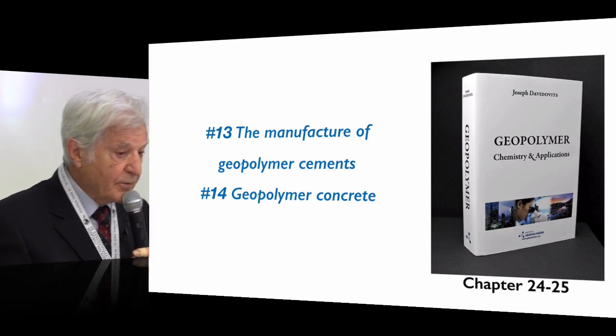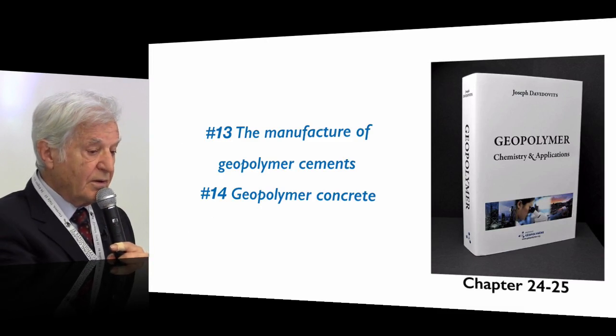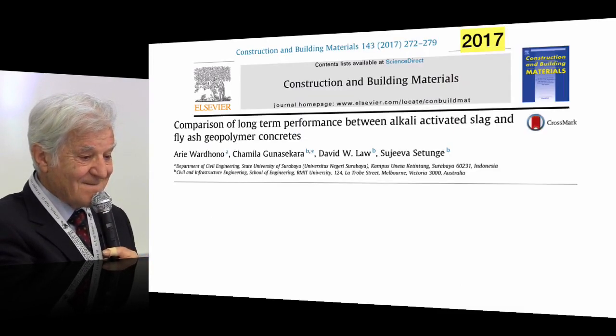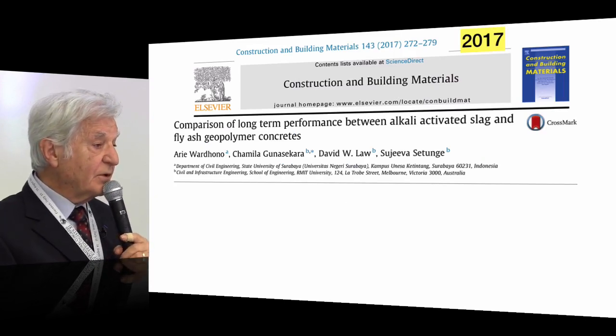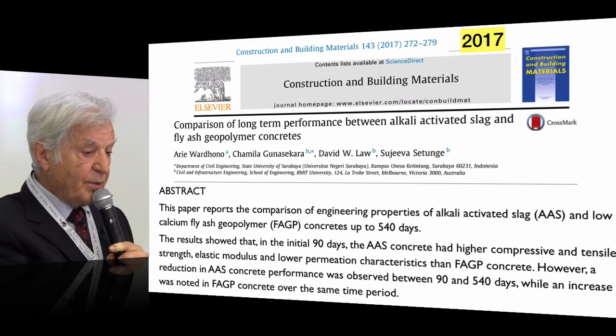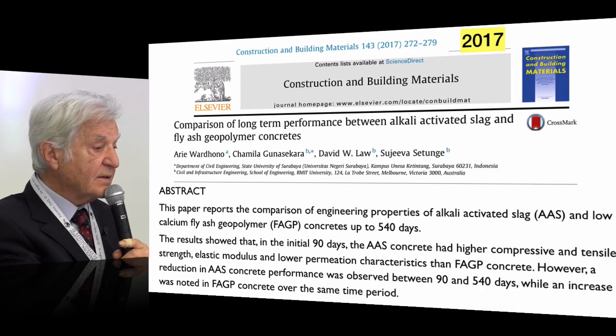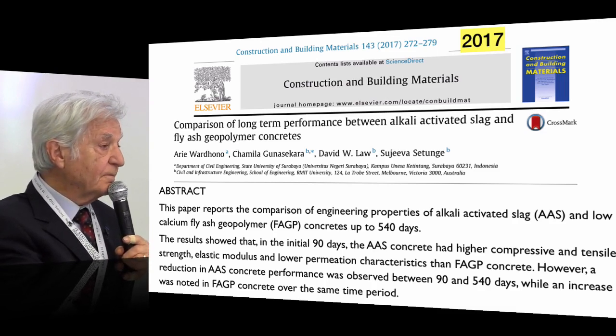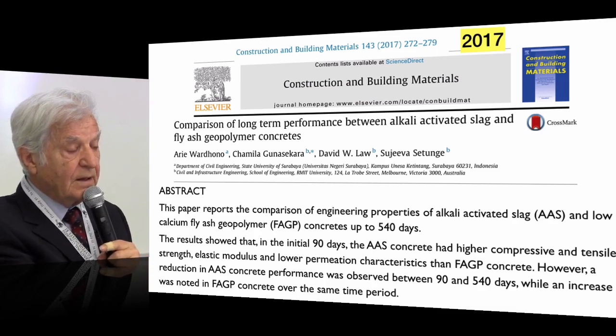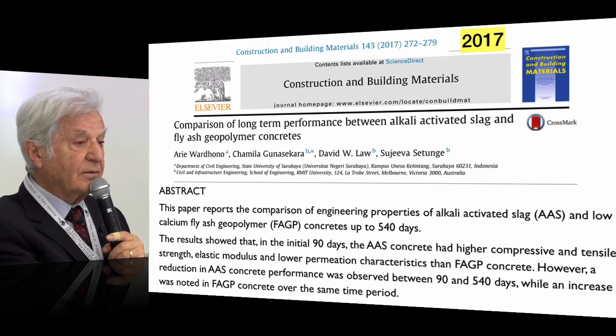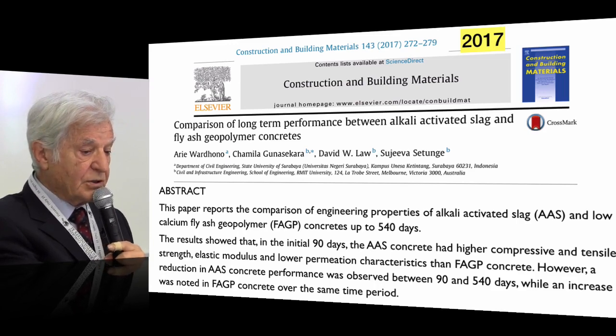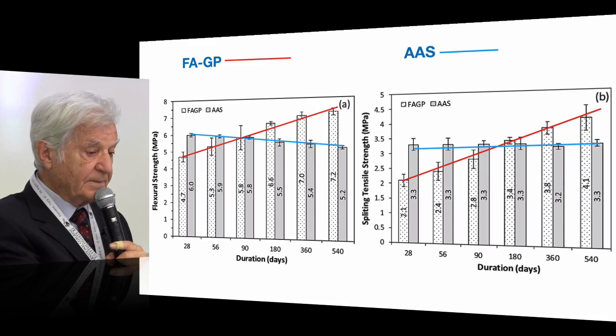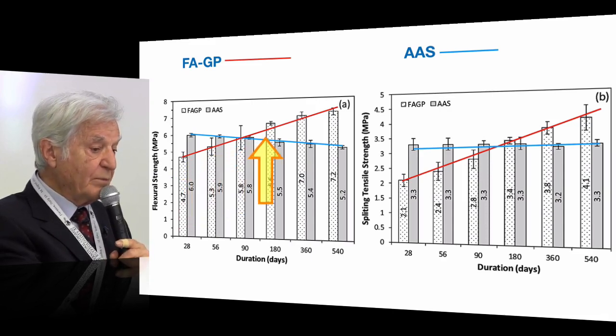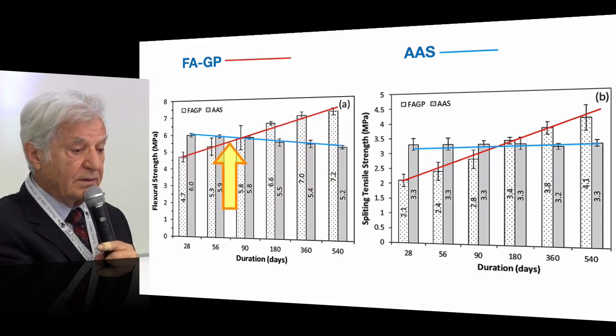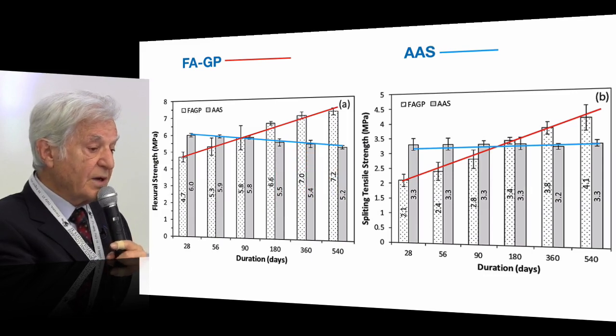Topic number three, the manufacture of geopolymer cement and the manufacture of geopolymer concrete. I present here a paper that I found very interesting. 2017, comparison of long-term performance between alkali-activated slag and fly ash geopolymer concrete. So they took both systems and looked at them after 540 days. This had not been done before.